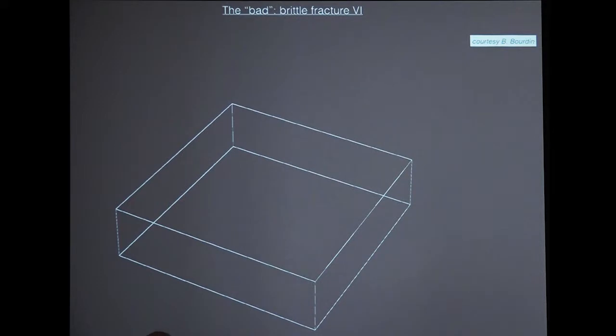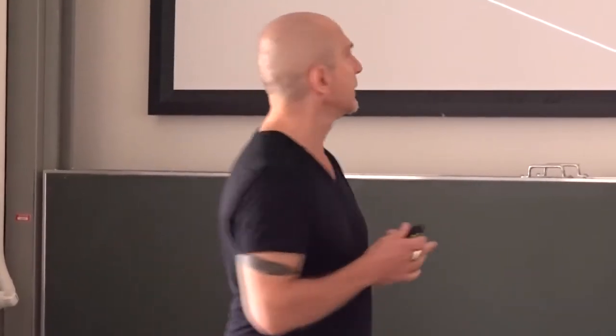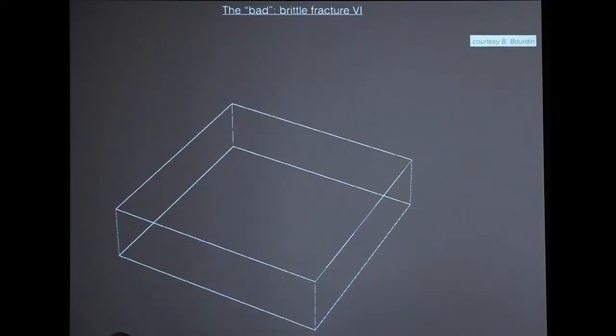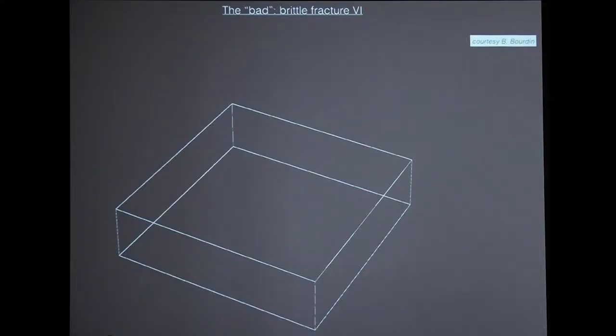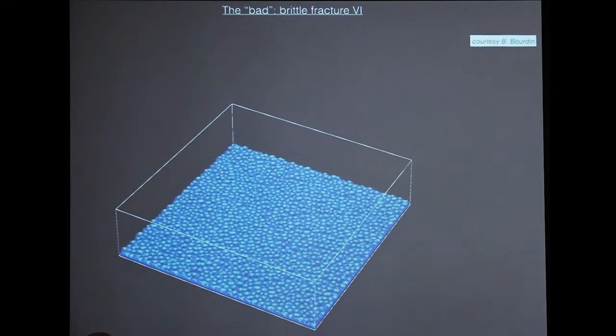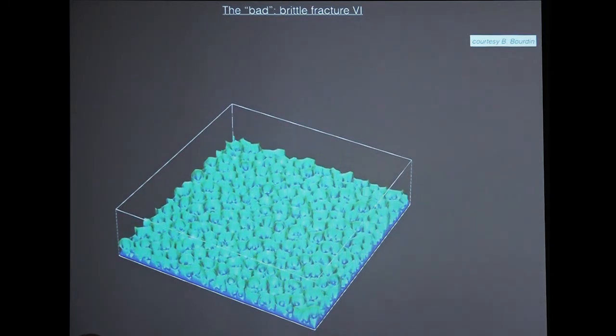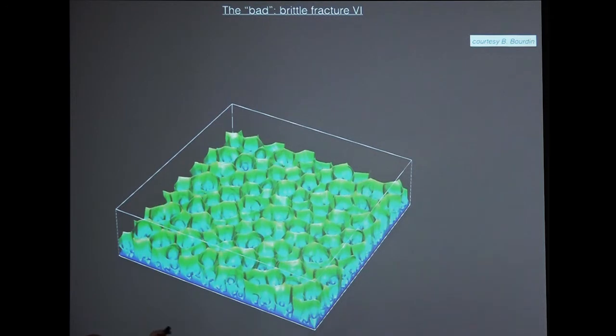So just for fun, same experiment, but in 3D. You take a plate and you put it on a bed of ice, but this time it's a 3D plate. Okay? And what I'm going to show you is a crack as it moves up. And this is a computation, a very heavy computation by Gilles Francfort. So I'll show you how the crack moves as time goes. So first there are no cracks, and then you have initiation, and the crack moves, and there's a coarsening process, and this is a crack.